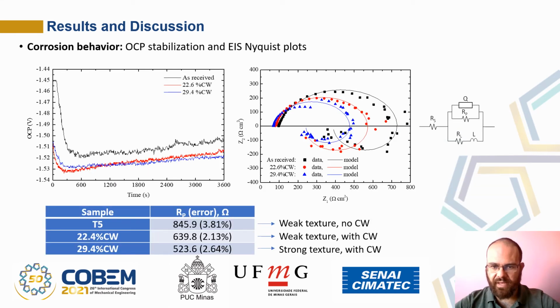Moving on to the corrosion behavior, the samples which were selected for analysis were the T5 as received, the 22.4% cold work, and the 29.4% cold work. The reason for this was because for the as received sample we had no significant texture components and low texture strength. For the 22.4% cold work we had strain hardening and a weak texture component, and for the 29.4% cold work we have more or less the same level of strain hardening concerning the tensile results, and the same texture component as the previous sample, but with a much higher texture strength.